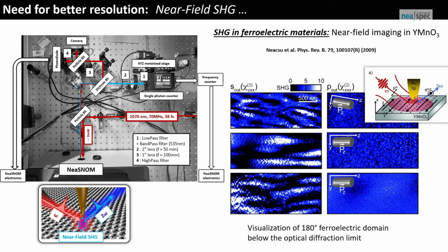But these single photon counters deliver a TTL output, and then we had to go through the single photon counter to the frequency counter and then to the neaSNOM electronics. So we cannot really use lock-in detection, but you will see in a minute. And for a little bit of technical detail, here we have a very small active area of 50 microns, because we want a small dark current, which is in this case around 7 counts per second, not too bad.